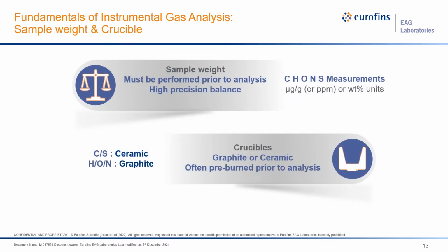The next step involves sample weighing. Precise and accurate weighing is mandatory since final measurements are provided in microgram per gram or weight percentage. Two types of crucibles are used for gas extraction. Crucibles are often pre-burned to remove any gases absorbed during storage. Also, note that ceramic crucibles are used for carbon and sulfur analysis, whereas graphite crucibles are used for hydrogen, oxygen, and nitrogen analysis.